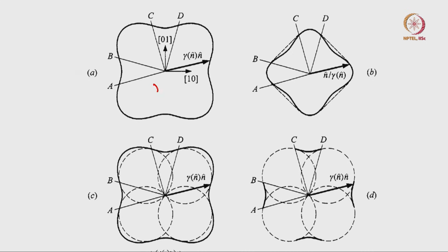So, this is gamma as a function of n, right. So, gamma as a function of n, this has the least energy, this has again least energy, this has again least energy, but then the energies start increasing, right. So, this is still a surface which does not have cusps like I was showing you, but you can assume that they have smoothened it out a bit, right. So, this is more close to isotropic surface, but there is anisotropy. Okay. So, now in such a surface, what I am going to do is I am going to plot the gamma inverse, 1 by gamma.